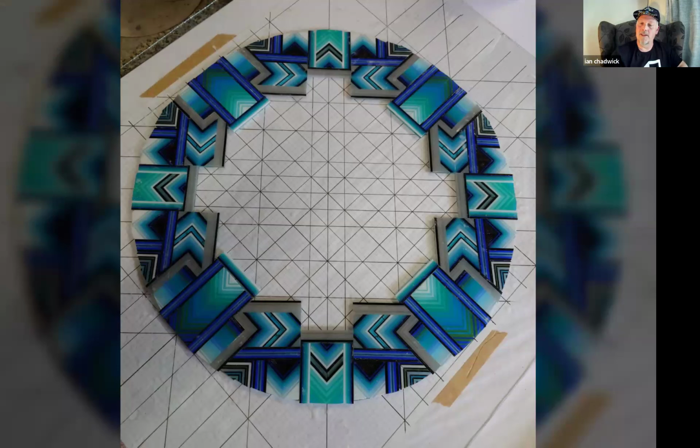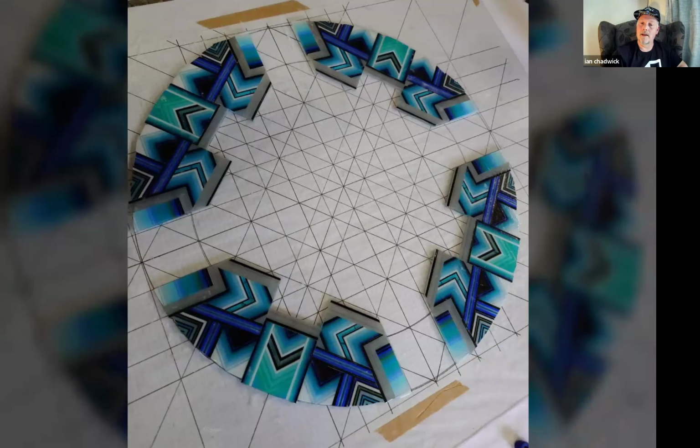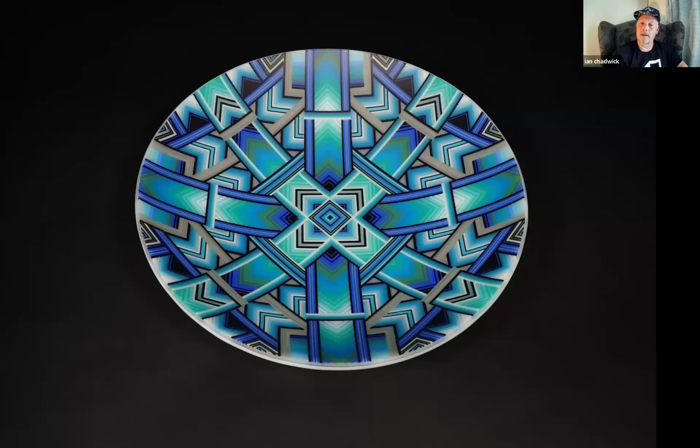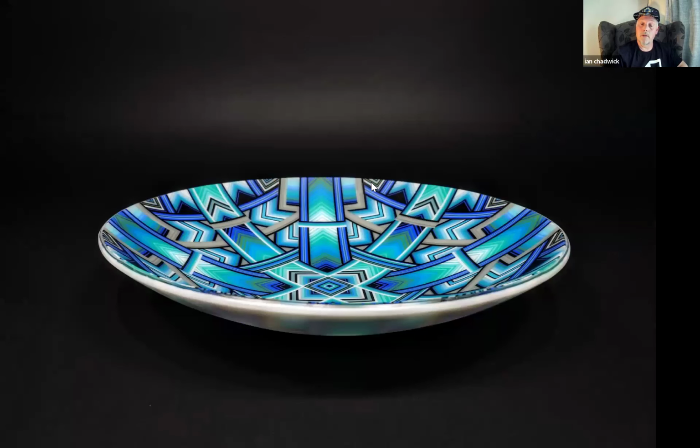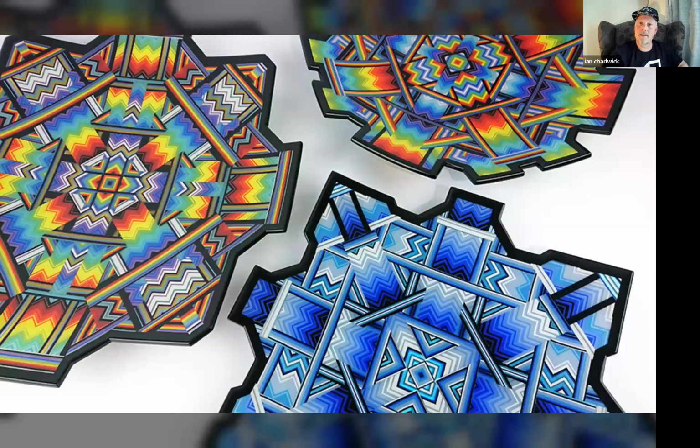And it always leaves these quite interesting voids within the middle of the patterns. Again, you can see that. And that's a finished piece. Again, cold worked on the surface to create this satin effect, backed with white opalescent glass, with transparent elements within that, so there is some depth on the surface. In areas like here, this is a transparent color amongst the opalescent stringers, so there is depth within that surface effect as well. Again, another view of the same bowl, and that's me.